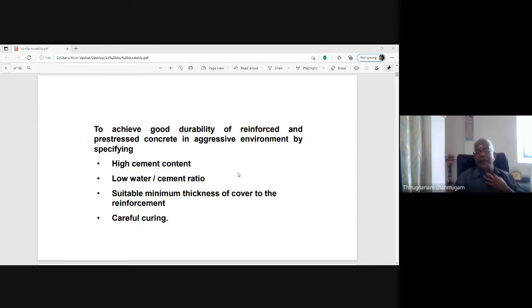And at the same time, the water cement ratio is also mentioned in the same table, the maximum water cement ratio for the different exposure conditions. For mild exposure condition and moderate exposure condition, the water cement ratio may be 0.5 or 0.45. But for the severe and extreme exposure condition, it is limited to 0.4. The maximum water cement ratio is limited to 0.4. So you can normally adopt 0.3 to 0.4 depending upon the grade of concrete.